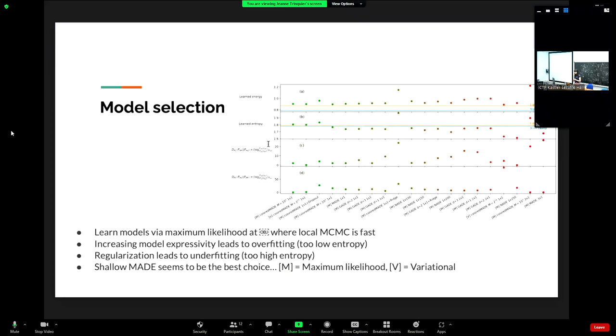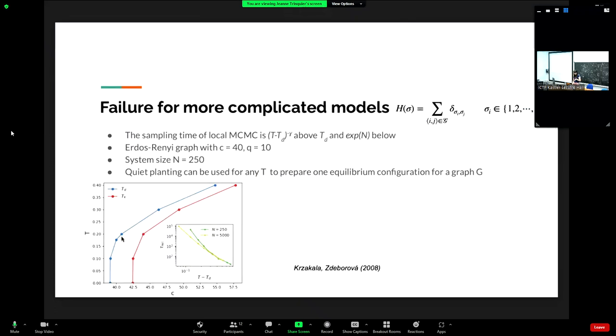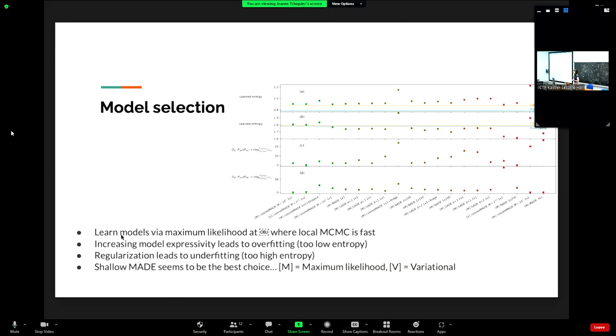So what we did is first to do some model selection. At a high temperature, T equal 1, where the critical temperature is around 0.2, so way higher than the critical temperature, we tested a lot of models that are present in the literature to select a good model. The first two plots show the learnt energy and the learnt entropy of many different models. The goal is to be as close as possible to the yellow line, which is the equilibrium value. You see that at this temperature, there are a lot of models that are quite close to the true value.